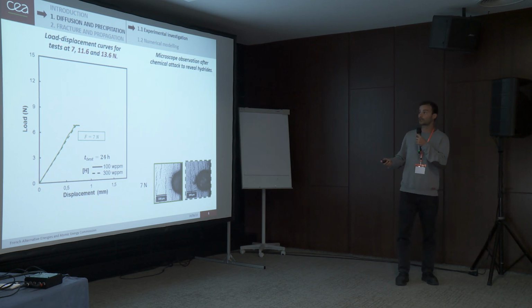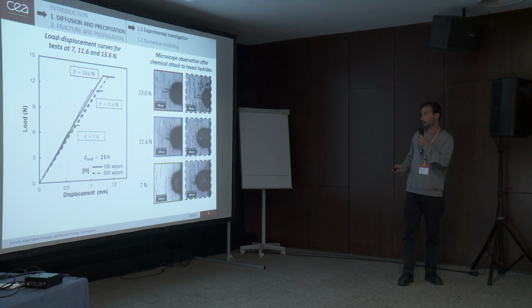I will show you the load displacement curves for tests at 7, 11.6, and 13.6 Newton, and the microscope observation associated with those tests after a chemical attack to reveal hydrides. So here you can see results at 7 Newton, 11.6, and 13.6. As you can see, there is no crack initiation for any of those tests, so they were stopped after 24 hours. And we can observe two things.